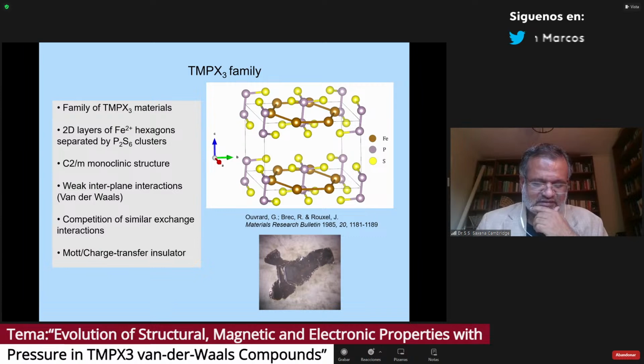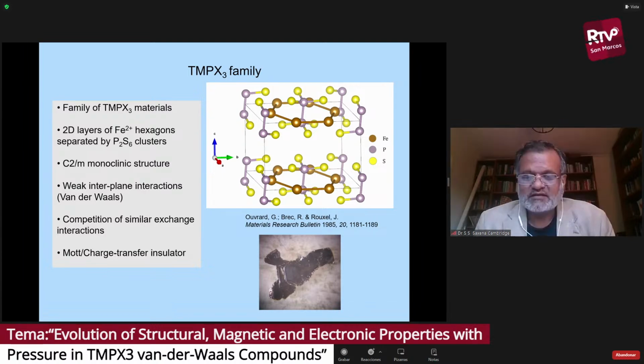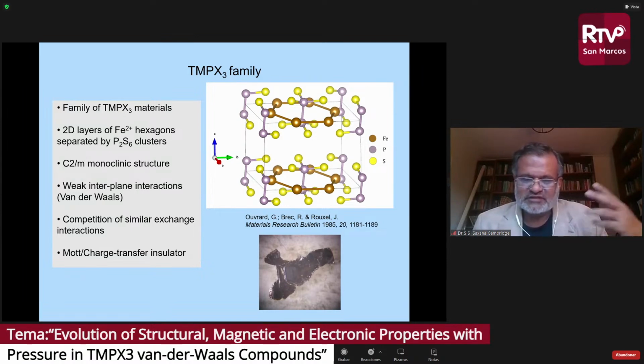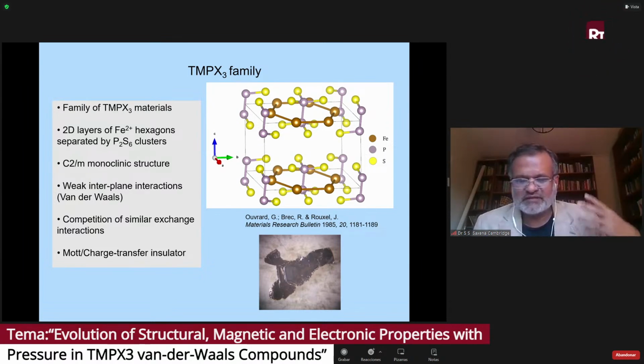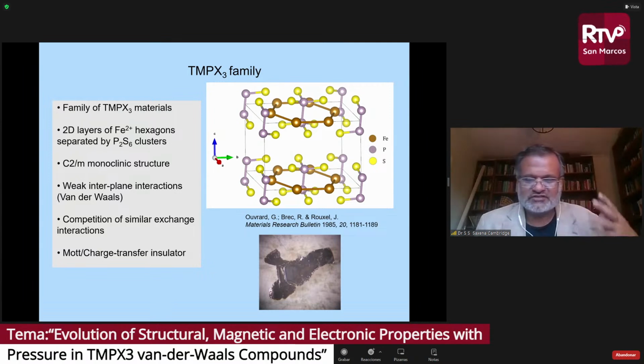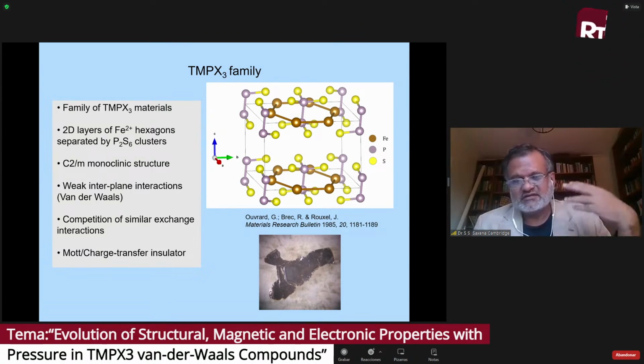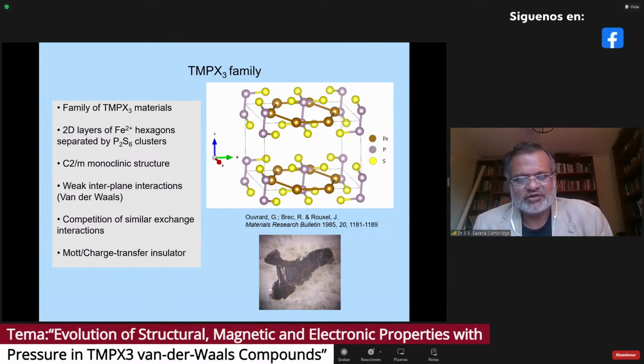And we searched for a while for a viable system where we could do the clean tuning, meaning that the disorder and various other aspects that emerge due to intercalation and making samples which are air sensitive, and many restrictions that came in, we wanted to remove them and return to working with materials which had, first of all, magnetism, second, potential for correlated physics, and third, that they could be tuned towards a critical point or dimensionality crossover. And we were quite lucky to find this TMPX3 family, which I will show a little bit about.